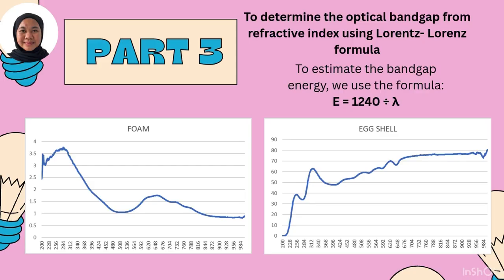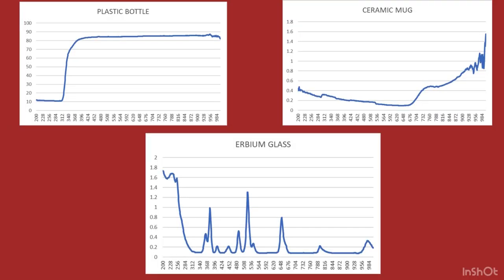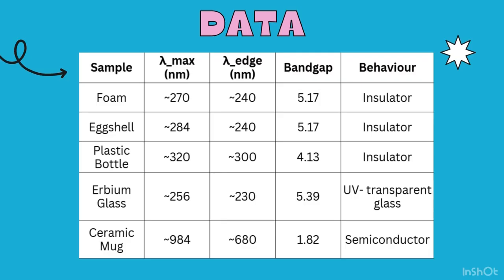From the graph, we identified the absorption edge where the material starts absorbing significantly. So this was the example of the graph. From the sample, foam, the lambda max in nanometer is 270 and the lambda edge is 240. The band gap is 5.17. It behaves as insulator. For eggshell, the lambda max is 284, the lambda edge is 240. The band gap is 5.17 also, and it behaves also as insulator.